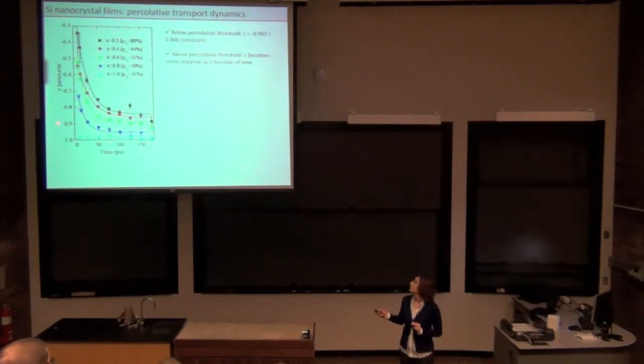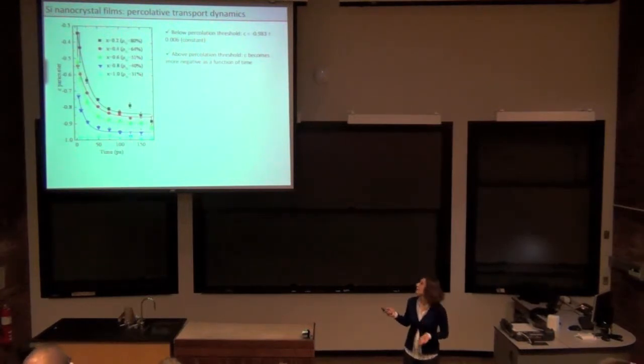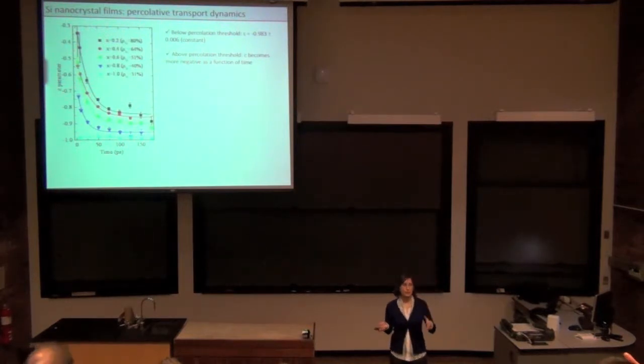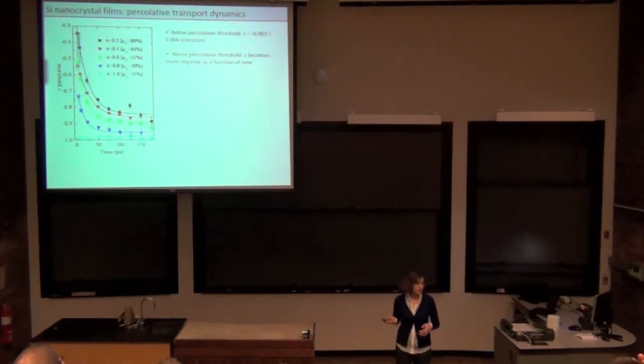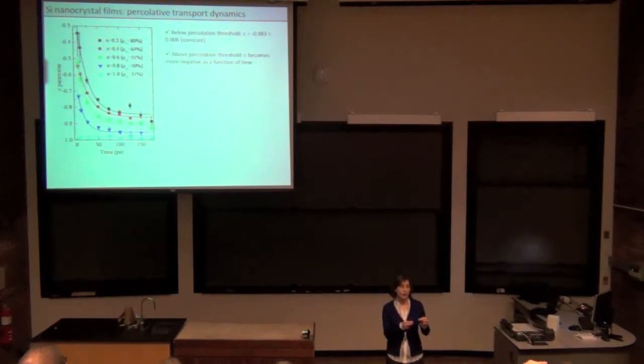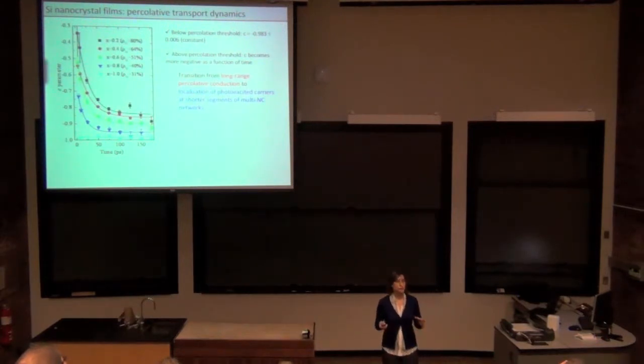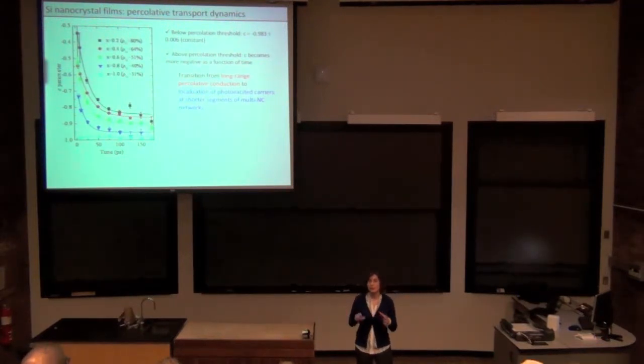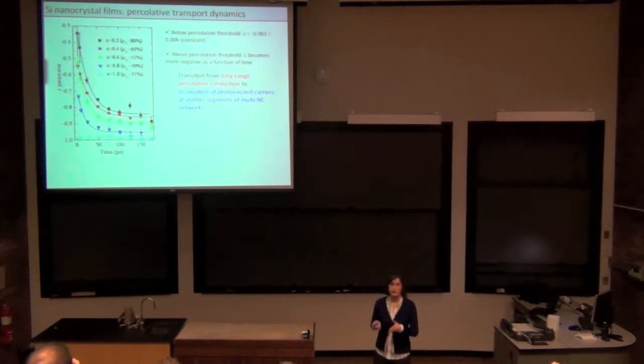Two things here. First of all, this curve, it's not really a curve, it's a line, for the sample with the silicon content below the percolation threshold. It doesn't change. It starts off very close to negative 1, and just stays there. But for the other samples above the percolation threshold, the carriers start out being quite able to travel far along these pathways. But as time goes on, we see an increasing degree of localization. So what we see is some sort of transition from long-range percolative transport to increased localization in segments of these